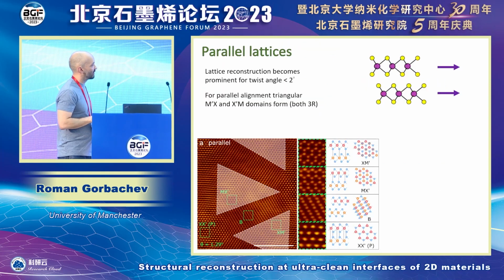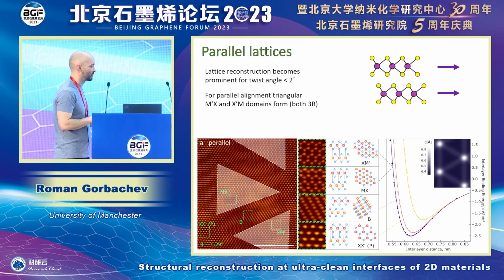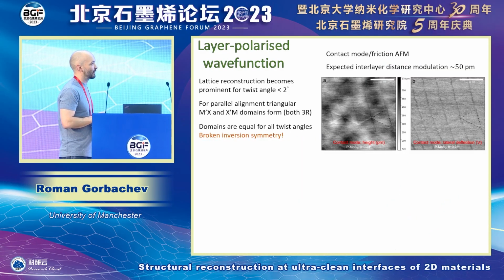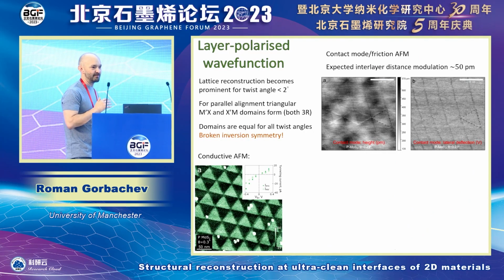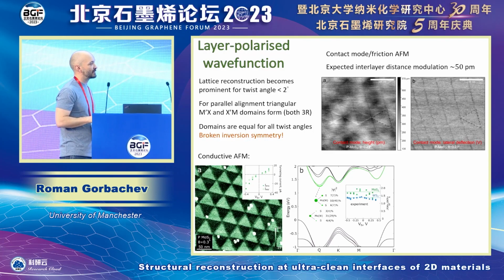Now, if you look at the parallel alignment, what we see now, we see two equivalent domains, but they are not the same. So the stacking looks very similar, and the energy of the stacking is actually the same. So here, the two curves overlap in terms of the energy, but they are mirror reflection of each other, and they don't have mirror symmetry. And what that means in kind of physical terms, right? Because you don't have mirror symmetry, you can now have a wave function that is asymmetric with respect to the two layers. So for example, if you take a conductive state at the bottom of the conduction band at Q point, this state will be more based on, for example, top layer than the bottom layer. And in the opposite domain, you have this state sitting on the bottom layer and less on the top layer. So if you do tunneling experiments with conductive AFM, you see a huge difference in tunneling current